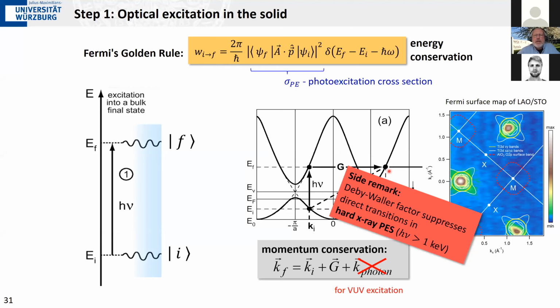You can beat the Debye-Waller factor by going to very, very low temperatures, so it increases the efforts that you have to put into your experiment. But just to give you an order of magnitude, as soon as your photon energy goes into the kilo electron volt regime, it becomes difficult to maintain momentum resolution. But it's not completely impossible, and we have done recently experiments at very high photon energies where you still see some k-space information, but I will not address it here, and that's really under very special conditions.